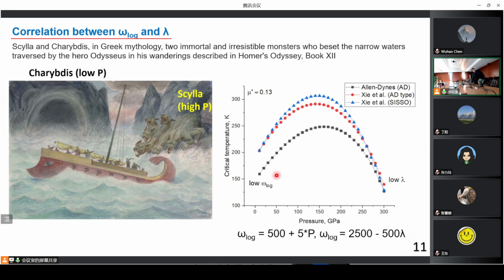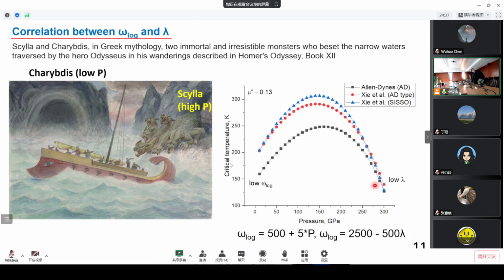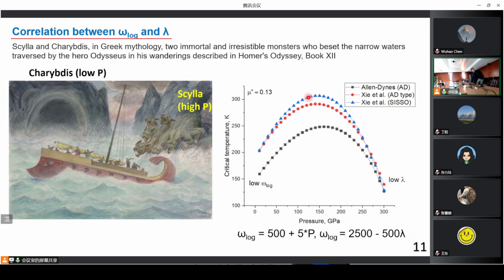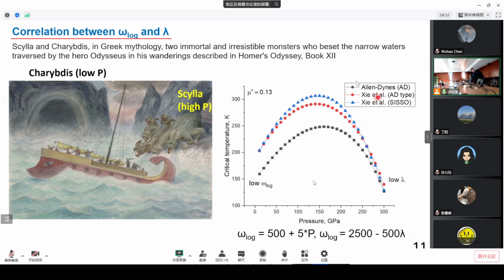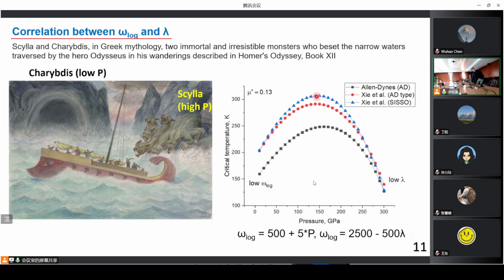The left side is low pressures, where the problem is that we have very low logarithmic frequencies, so we cannot achieve high TC. In the opposite situation, at high pressures, due to this correlation, we will have a low EPC coefficient, a low electron-phonon coupling. Again, we cannot reach high TC. So the optimal region is between them, about 150 to 200 GPa, where you see the maximum. According to these models, the maximum TC is about 300 Kelvin. So in principle, I think we can reach room temperature superconductivity, but it's really complex, and that's the end of this story. So LaH10 is quite close to the maximum. You see it's 250. It's exactly this model, and we have maybe 50 degrees at most. That's all that we can get from hydrides.